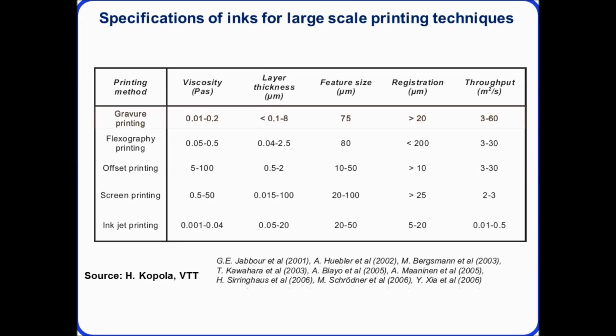Once we form these dispersions, we formulate different inks for different printing processes. The most common ones we look at in Cambridge are screen printing, inkjet printing, and flexographic printing. If you want an ink which can satisfy these printing processes, then we can look at the high scalability of printed electronics. Each of these techniques will need different viscosity requirements. They have different throughputs, and therefore can be used to target different application areas, but also what's key is the feature size. With processes such as inkjet printing, we can print the finest features down to around 20 microns. With screen printing, we're typically getting around 75 to 100 microns resolution when printing track widths.